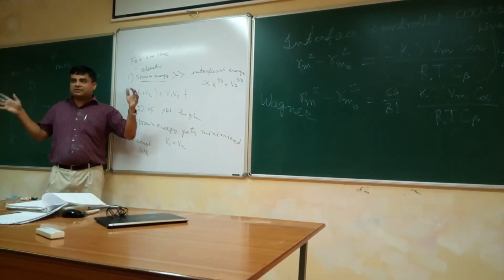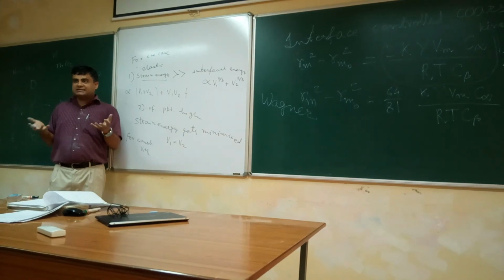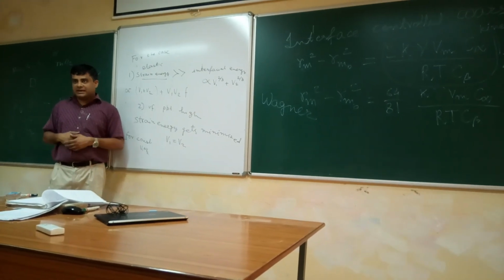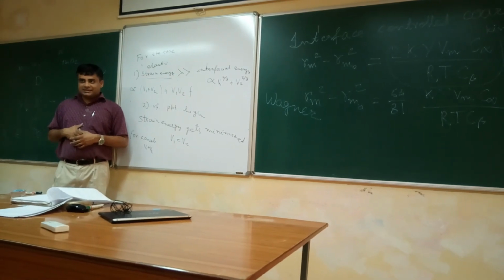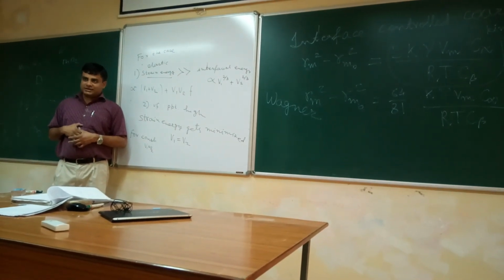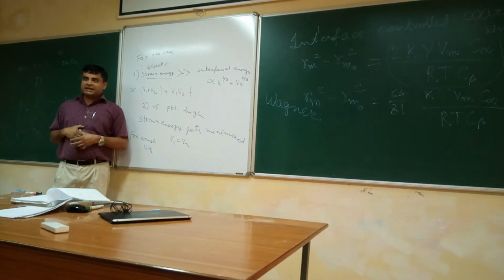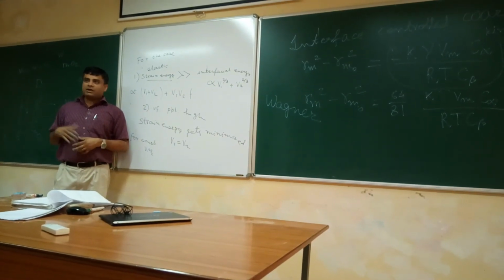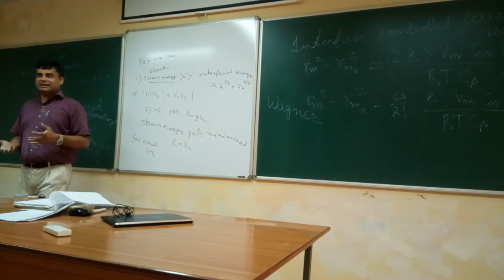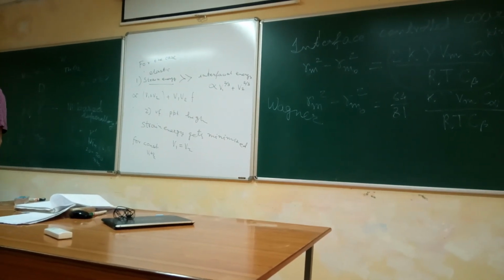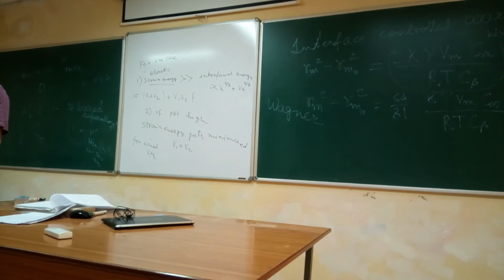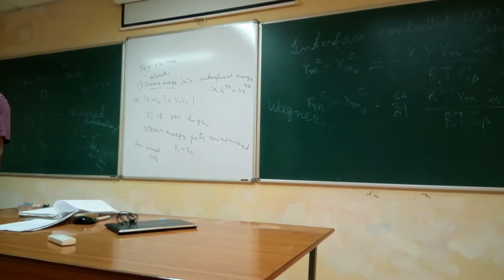If there are multiple precipitates and all their volumes are equal, the strain energy will be minimized. So in that case, it is going against coarsening. Coarsening is what? Whichever of V1 or V2 is larger will keep on growing and the other one will reduce. So this is called elastic stabilization.